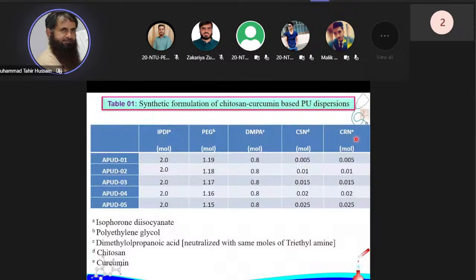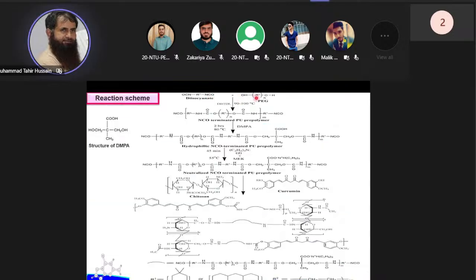Actually, in this research work, we have used blends of chitosan and curcumin, increasing the amount in every incoming sample. First, we prepared the pre-polymer by reacting the isocyanate with the hydroxyl groups, which is formed by the reaction of NCO and OH groups, which is further reacted with the dimethylol propionic acid. We use the hydroxyl groups of these materials to further extend this material. This is the dimethylol propionic acid, which is already incorporated into the pre-polymer, and in the next step we neutralize this material with the triethylamine.